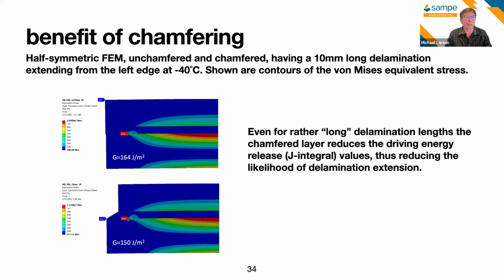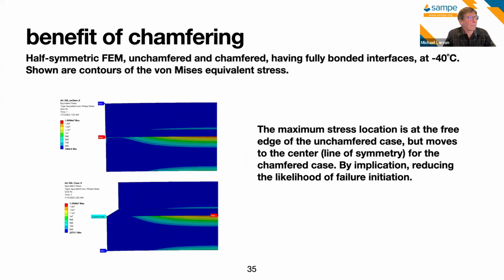Maybe you can do something to make the adhesive happier, more accommodated. When we put the chamfer in a specimen without an initial flaw, as best we could tell by the finite element model, the maximum stress remained at the surface of the non-chamfered one. With our chamfer, though, the maximum stress actually moved to a place interior to the specimen.